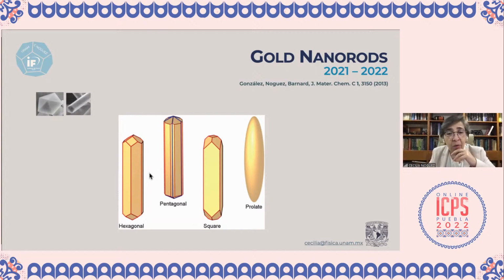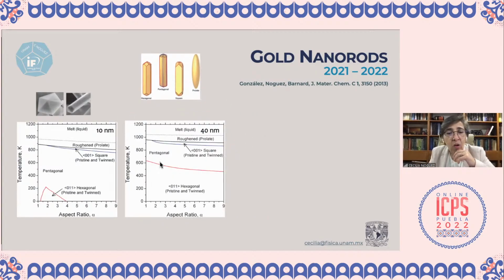Here we also have this symmetry of the nanoparticle, but another important ingredient is the width as compared with the length of the nanoparticle. When we look at the energy equilibrium to grow this kind of nanoparticle, for small nanoparticles, equivalent for example to the volume of a sphere of 10 nanometers, as a function of the temperature and the aspect ratio, that means the length as compared with the width, we have that for small aspect ratios we have the hexagonal nanoparticle, then the pentagonal nanoparticle when we increase the temperature, and finally the square and some kind of prolate, where the shape is lost because of the heating.